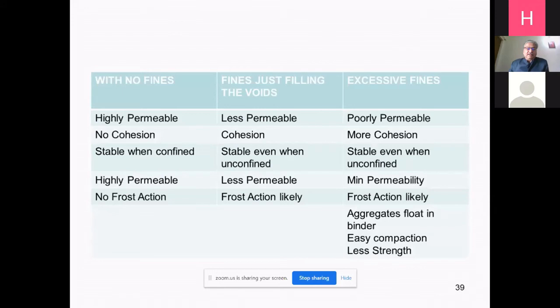With no fines, it is highly permeable. When fines just fill the voids, it is less permeable. When excessive fines are there, it is poorly permeable. Permeability is high when you have sand or coarse aggregate. When there is clay, the permeability is less and the drainage is also less. But when there are no fines, the cohesion is very less. It is difficult to place the material when it is not confined, because the material will come out from the sides. For example, if you just take one practical example, if you put the aggregate like sand in the shoulders,